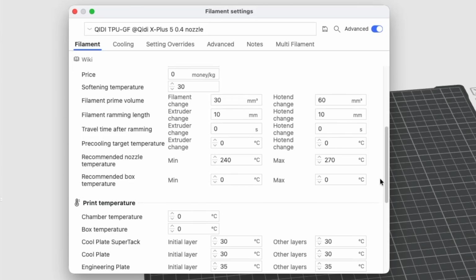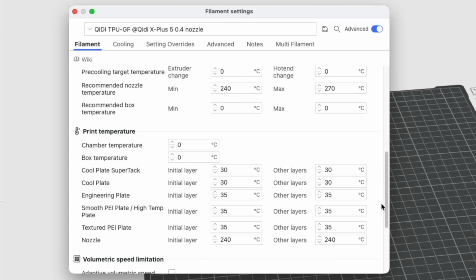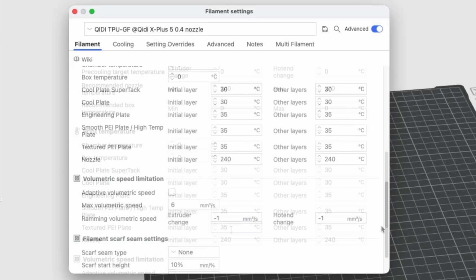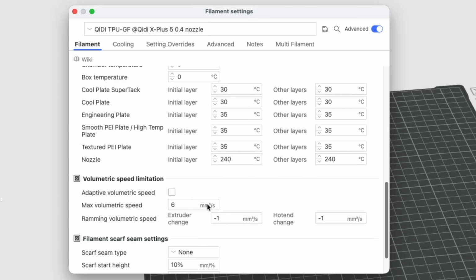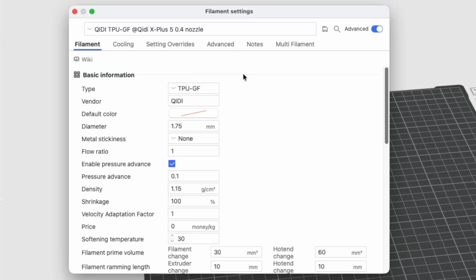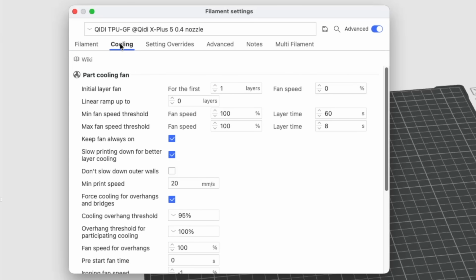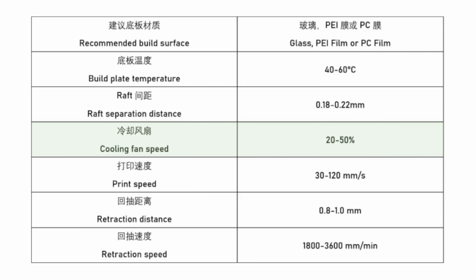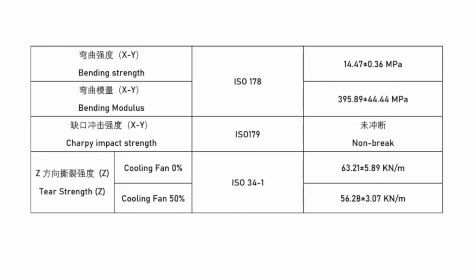The hot end temperature was set to 240 Celsius, which was at the bottom of their recommended range, and the bed was set to 35 Celsius, which is actually lower than the recommended range that they had listed in their TDS. The max volumetric speed was set to 6 cubic millimeters a second, so fairly conservative, and while they had the auxiliary fan set to off, the part cooling fan other than the first layer was set to 100% cooling. This was a little surprising considering their recommended range was between 20 to 50%, and their own test showed that the parts printed had a higher Z tear strength with no cooling at all versus the one with 50% cooling.